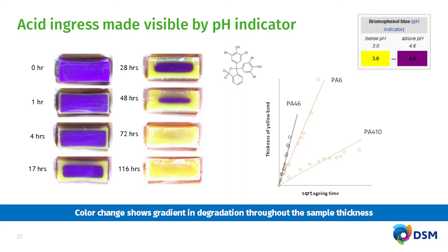For a polymer material with a certain thickness, chemical degradation does not happen instantaneously throughout the whole thickness of the material. So we also need to take into account the speed of diffusion of the aggressive species from skin to core. To highlight this important topic, here I show you some tips and tricks that we do with our polyamide. We compound a pH indicator, in this case bromophenol blue, together with polyamide. After we make the compound, we injection mold it into tensile bars like what you see in the left figure. The tensile bar looks purple because bromophenol blue stays purple when the ambient pH is above 4.6.